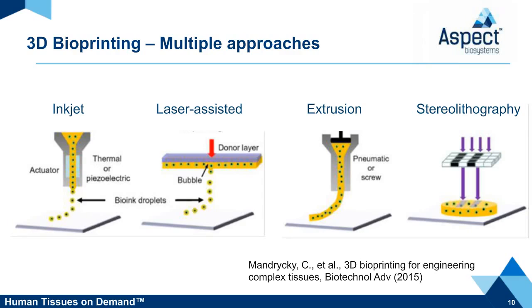Extrusion bioprinting is probably the most common type of bioprinting technology in use today. This is where a higher viscosity bioink is extruded through a syringe needle. The shear stresses introduced into the system during that extrusion sometimes reduce cell viability and also restrict the speed of printing. Stereolithography is one more type of bioprinting, and this is where light, often ultraviolet light, is used to cross-link liquid bioinks to form a solid structure.